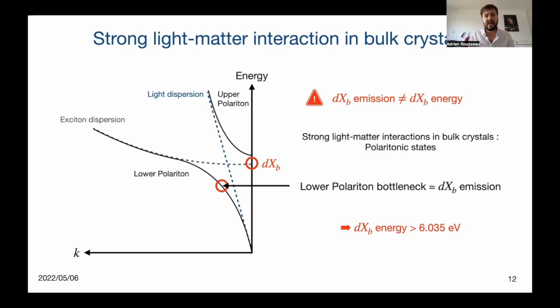To be more precise, the excitonic dispersion has been represented on the left by the gray dashed line in momentum space, following the k-axis. The light dispersion has also been represented in a bulk crystal by the blue dashed line in momentum space. Because of the strong light-matter interaction between light and exciton, the two dispersions will anticross, forming two polaritonic branches, namely the upper polaritonic branch and the lower polaritonic branch respectively, represented here by the black solid line in momentum space.